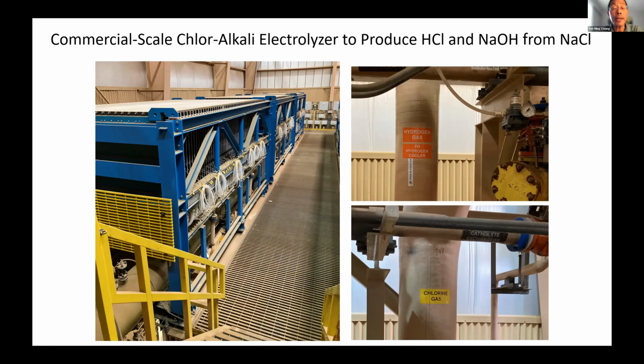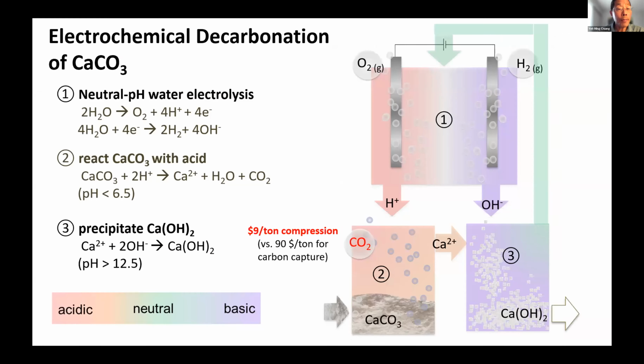You can recombine the hydrogen and chlorine to make HCl, and because you feed this device with a salt solution, NaCl solution, you therefore produce hydrochloric acid and sodium hydroxide, the acid and the base. Okay? Now, what could you do if you had both of these? Right? So the idea we conceived was that we could use the acid to decompose the metal carbonate.